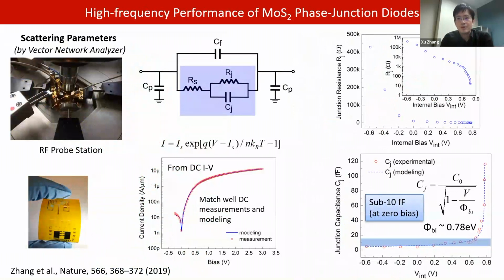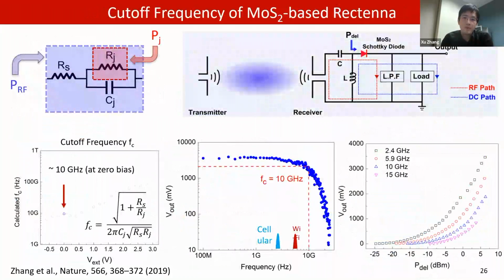We also characterize the high frequency performance of the device by measuring its S parameters using a vector network analyzer. A very important parameter for the device speed is the junction capacitance. Near 0 bias operation regime, the junction capacitance of our device is below 10 femtofarad, which is roughly 10 times smaller than alternative technologies. From this, we can calculate the cutoff frequency of the MoS₂ Schottky diode. At 0 bias, it is about 10 gigahertz.